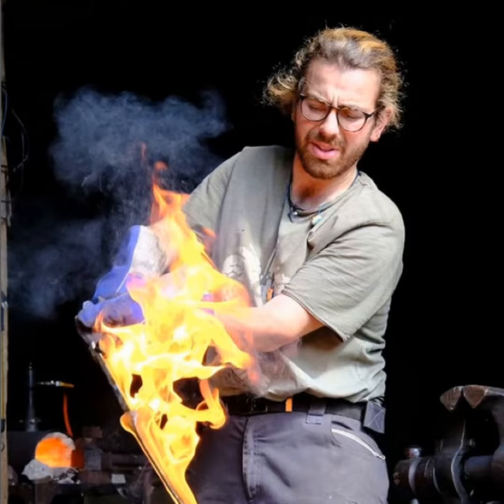But what I noticed, and this is actually kind of cool, if you polish it on a stone, you see the rust as little inclusions between the layers, and it doesn't get a homogeneous piece. You can differentiate the layers just by the rust that you forge back into the billet. And I actually think it's kind of cool.